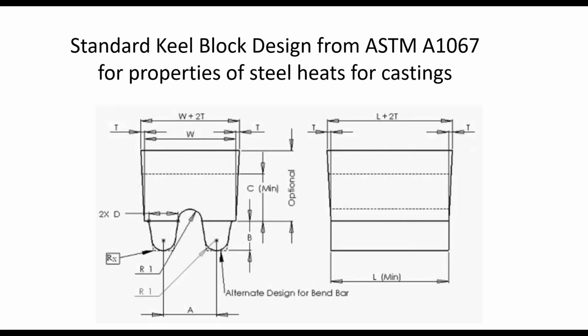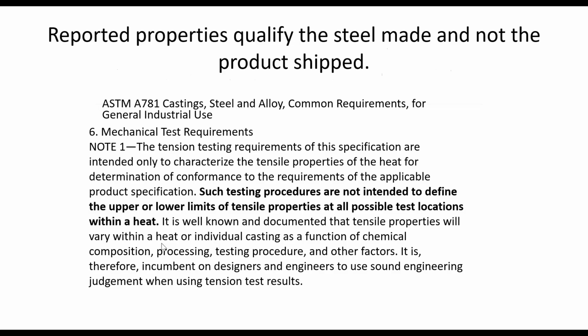Now, in steel castings, we pour a special keel block design that's designed so that it's sound. These legs are sound, and then we cut the legs off and heat treat them the way we heat treat the casting. That is the way we demonstrate our conformance to the ASTM specification. So if you order an ASTM grade 216 WCB, this is where I take the test material from.